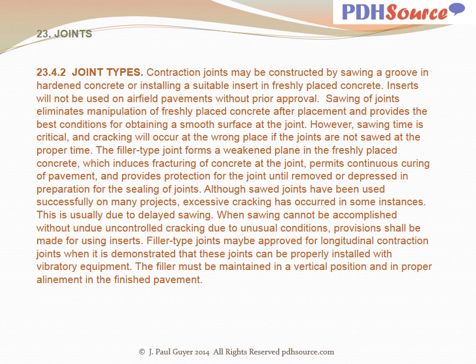The filler type joint forms a weakened plane in the freshly placed concrete, which induces fracturing of concrete at the joint, permits continuous curing of pavement, and provides protection for the joint until removed or depressed in preparation for the sealing of joints. Although sawed joints have been used successfully on many projects, excessive cracking has occurred in some instances. This is usually due to delayed sawing. When sawing cannot be accomplished without undue uncontrolled cracking due to unusual conditions, provisions shall be made for using inserts.